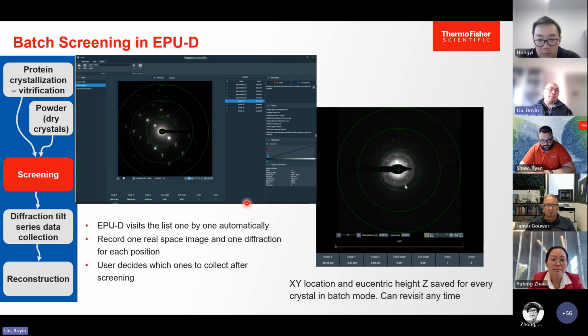And batch screening in EPU-D, so I've talked about that. This is a new feature for EPU-D. You've got the navigator here. I've added more than 50 crystals at a time, and the software didn't crash, so it's pretty reliable. You can just keep adding lots of crystals here, and then start the automatic screening run. Then check the diffraction patterns later, and decide which ones to keep.